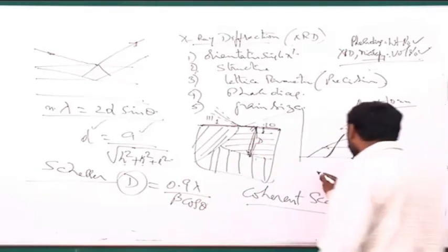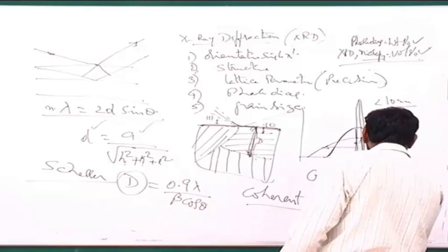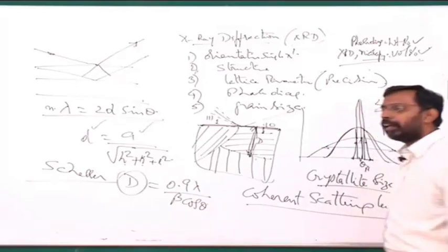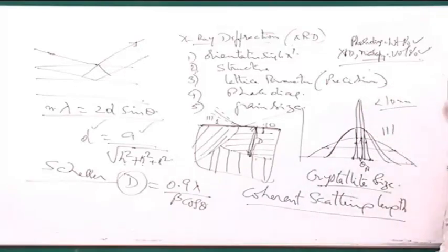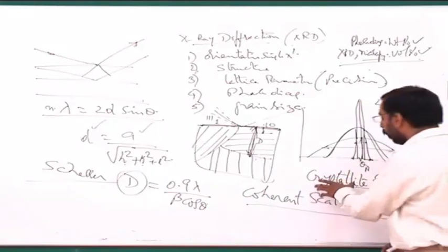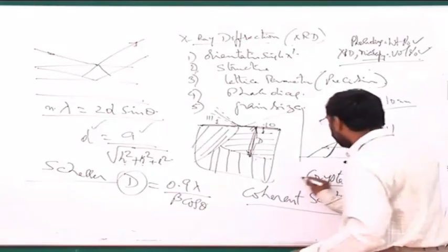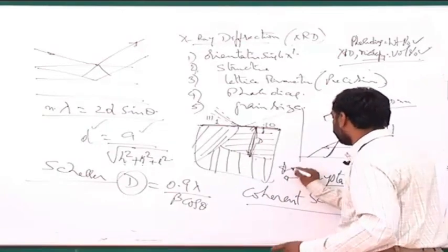And some people usually call it crystallite size. I need to give you these terms because this is different from what is called particle size. Many people get confused, particularly people working in powder metallurgy areas, who simply call this particle size. It is not particle size. A particle can be polycrystalline, and may have a number of grains inside it. So what you are actually measuring is the crystallite size, which can be considered a grain size.